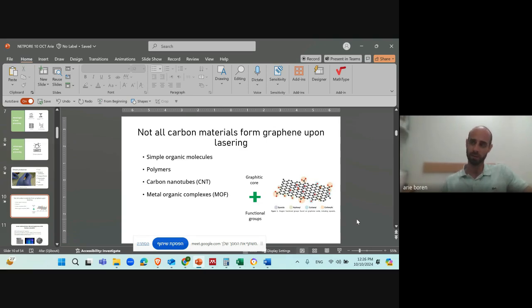but yet not all of them could undergo this laser processing. For example, carbon nanotubes that we tried didn't go. So the other component that you need is functional groups on the surface of your material that will react with the laser. So again, the mechanism is elimination of functional groups, heteroatoms, oxygen, nitrogen, hydrogen, exposing carbon atoms to form sp2 carbon-carbon bonds. Okay, this is the mechanism. So we need these two properties.